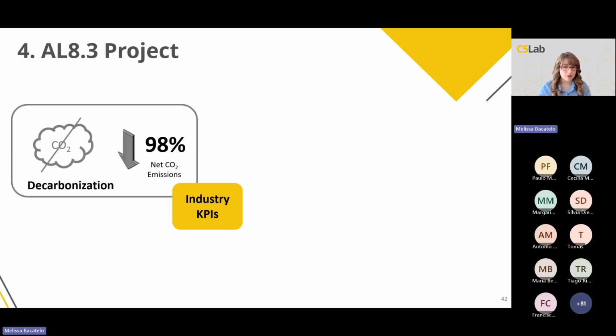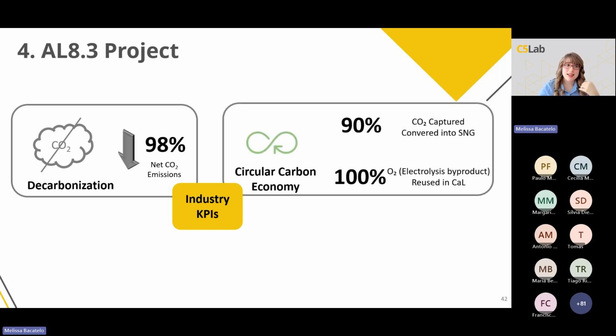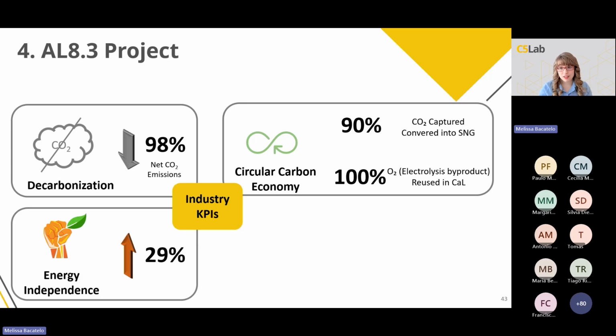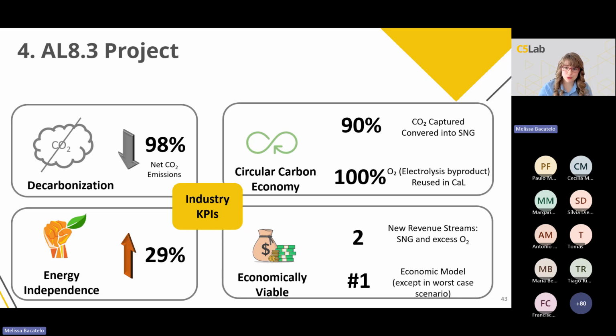So now let's see if we achieved the goals. First of all, the circular model reduces net emissions by up to 98% compared to the current model, converts 90% of captured CO2 into synthetic natural gas, and reuses 100% of the oxygen from electrolysis, thus contributing to the circular economy. In addition, it increases energy independence, and now we have 2 new sources of revenue through the sale of surplus synthetic natural gas and oxygen. This makes it an economically viable model, except in the worst case scenario.